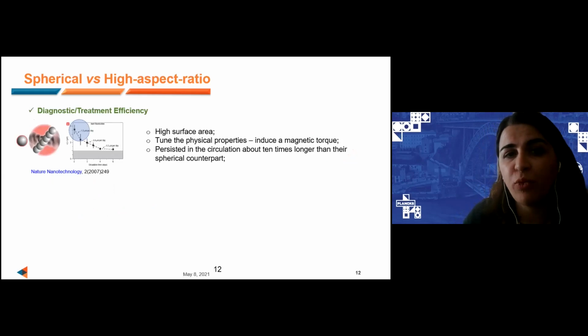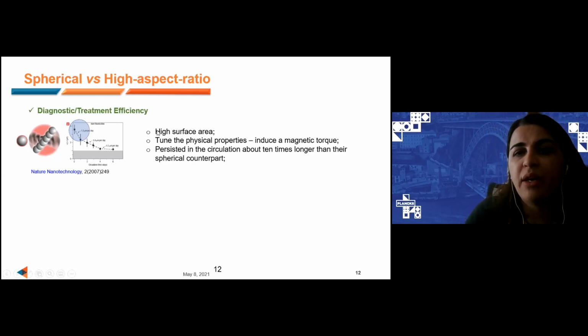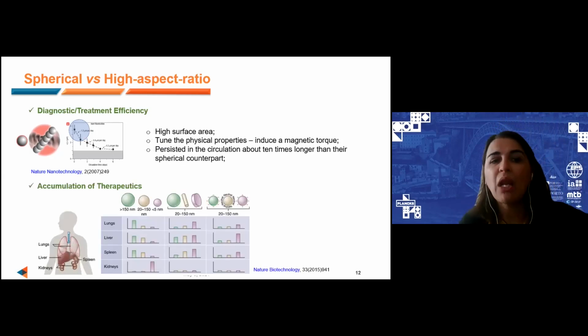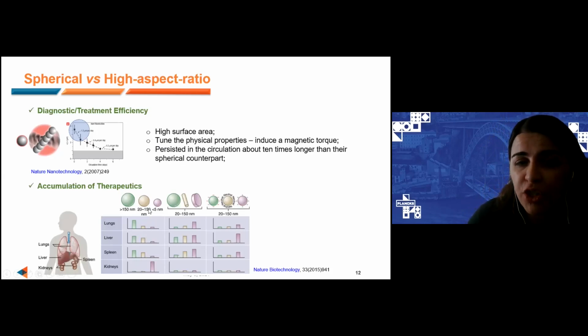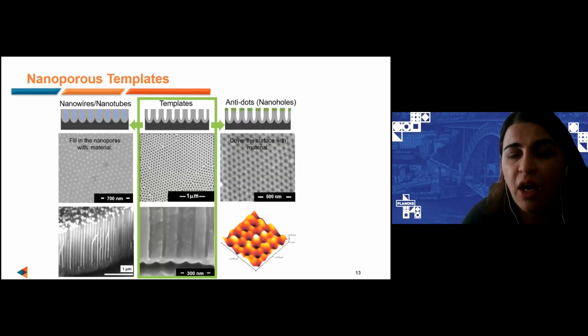Comparing spherical and high aspect ratio nanoparticles, we can see that high aspect ratio nanoparticles like nanowires, nanorods, or nanotubes present several advantages regarding the high surface area, the ability to tune the physical properties, and this kind of nanostructures also have a persistent circulation in our body. On the other hand, we also have to take into account the accumulation of therapeutics, and that is mainly determined by the size of the nanoparticles, their shape, but we can also play with the surface charge of the nanoparticles in order to reduce the accumulation of these nanotherapeutics.